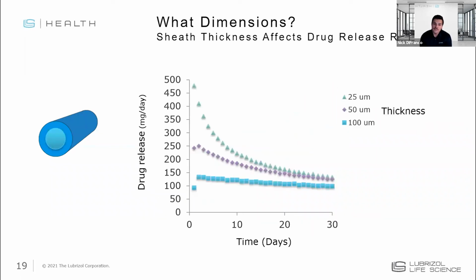And when you're designing core sheath systems, the dimensions of the overall device aren't the only factor you have to keep in mind. When you have a sheath around a drug-loaded core, the thickness of that sheath has a significant impact on drug release. If you think about a very thick sheath, in this case 100 microns, shown with the blue squares on the slide, what you see is a thicker sheath gets you closer to that zero order or steady state release over time. But as the sheath gets thinner, you get closer to resembling a matrix type implant, where the drug and polymer are homogeneously dispersed through the whole device, and therefore you get more and more of a first order release rate with a higher burst initially.